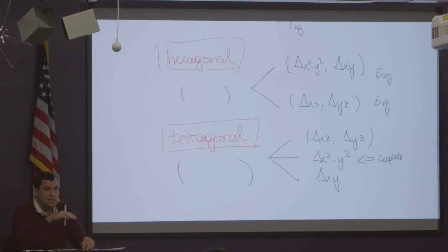I think Marcel Franz in his lecture is going to talk about twisted cuprates. And it turns out that if you take two tetragonal lattices and twist them by 45 degrees, the resulting group is not really tetragonal. It's non-crystallographic, a quasi-crystal. And then these two now transform as the same thing in this twisted system. And that's why you get these d plus id states and whatnot. Just to make a connection with a lecture that will come later.